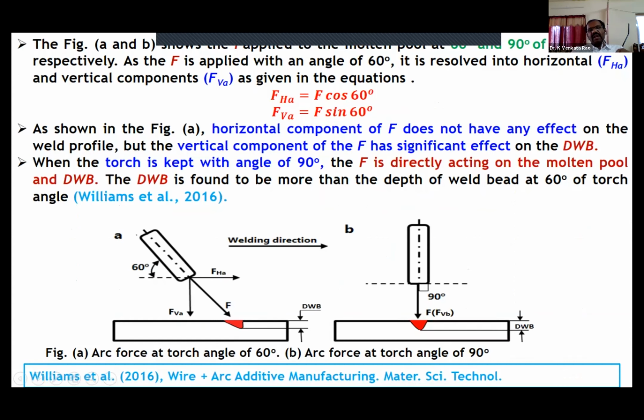See in the second figure, the total arc force is applied on the weld pool. That's why the depth of the weld bead is more. Actually, we don't want that much depth. If the depth of the weld bead is more, the height of the weld bead is decreased. Not only that, the width of the weld bead is also increased. When the arc force is more, what happens? Depth will be increased, width also increased, and the height will be minimized. So that is why it is not required. At 90 degrees this happened. When depth and width are increased, the height of the weld bead is reduced.